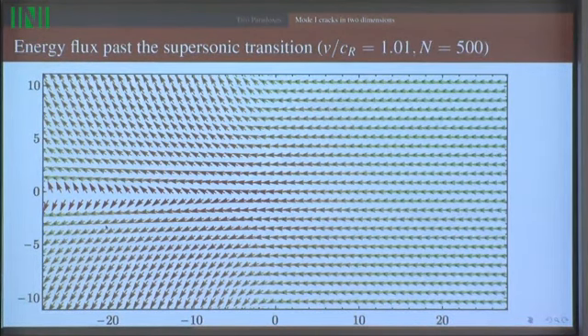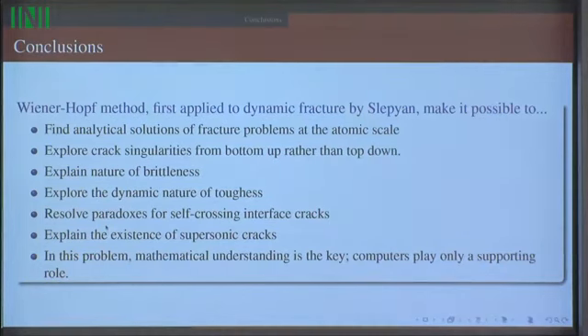The material ahead doesn't know it's coming because it's moving faster than the speed of sound, so there's no way for it to know. It can't establish the standard singularity. But at the atomic level, at least, and these atomic solutions completely contain linear elasticity, there's no problem. It finds the solution, and the cracks just move on.